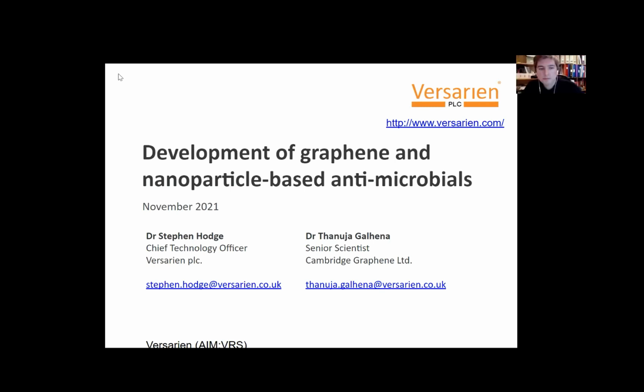Yeah, so I should just point out that silver itself is not being phased out, but there's things like silver nanoparticles, which are being phased out in Europe and possibly will be in the UK. So in terms of these mechanisms, the graphene that we've used as the control sample is non-functionalized, it's not graphene oxide, so it's got very little oxygen content. So there possibly will be different results if you were to use graphene oxide against the same bacteria or fungus.